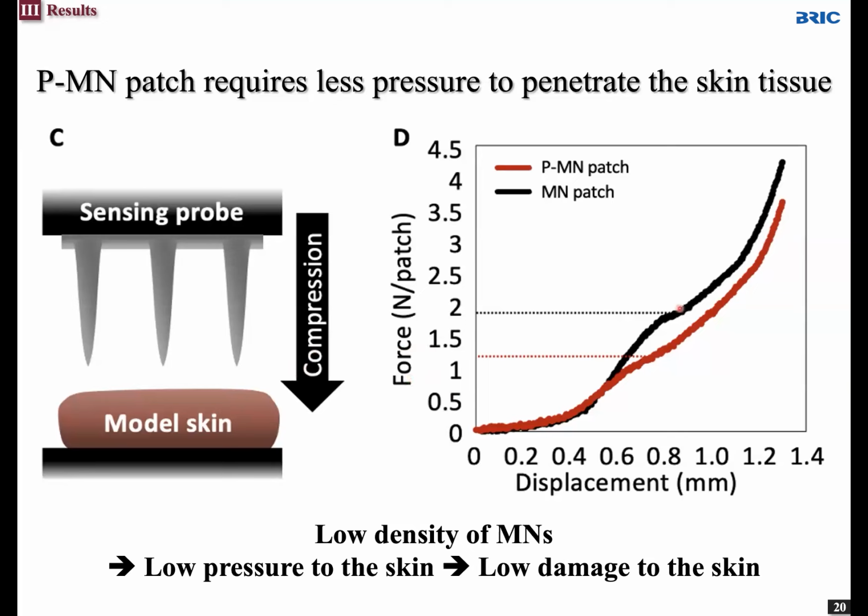Because the conventional microneedle patch here, in dark color, had a higher density of microneedles in the limited space, with our device, the peripheral microneedle patch here in red, the compression force required to insert the microneedles into the skin tissue was much milder than the force needed by the conventional microneedle patch.